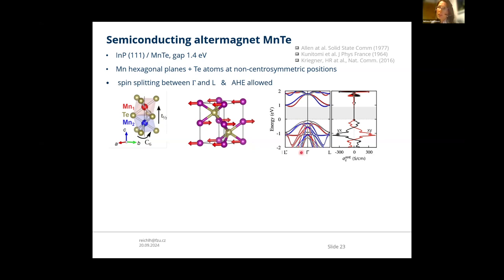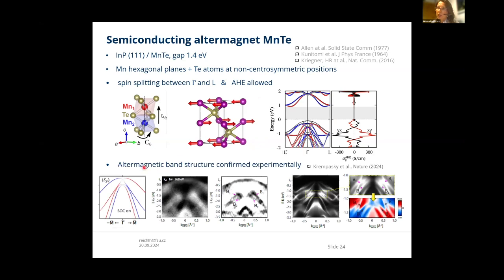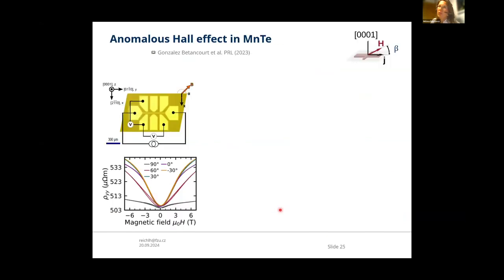And importantly here, because the spins are pointing not along the C direction as in chromium antimonide, but in the AB plane, the anomalous Hall effect is also allowed in zero magnetic field. The band structure in that case was confirmed by ARPES experiments by Juraj Krempanský and co-workers, the beautiful work which Libor also mentioned. So let me go directly to the transport measurements.